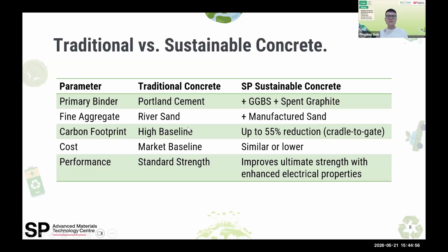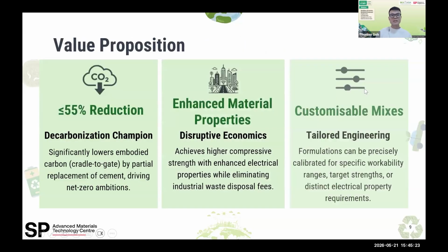And as for the cost, we put here similar or lower, because at this moment, we are not sure how the battery recyclers are going to price their spent graphite, but we are quite sure that GGBS is slightly cheaper than OPC cement. Then for the last performance, you can see that we also achieve the ultimate strength of 60 megapascal with the enhanced electrical property. So our value proposition here is that not only can we have a carbon dioxide reduction of up to 55%, we also enhance the electrical conductivity of the concrete.